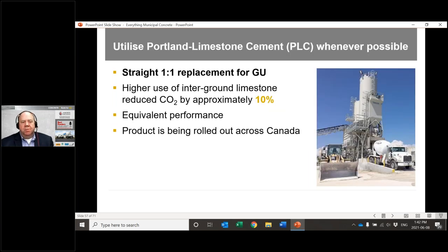Mentioned Portland limestone cement a few times. Again, we're probably at 50 plus percent usage here in Ontario, so we've had it for quite a while. Again, it's a straight one-to-one replacement from a concrete producer standpoint. There's nothing you have to change in the mix design.